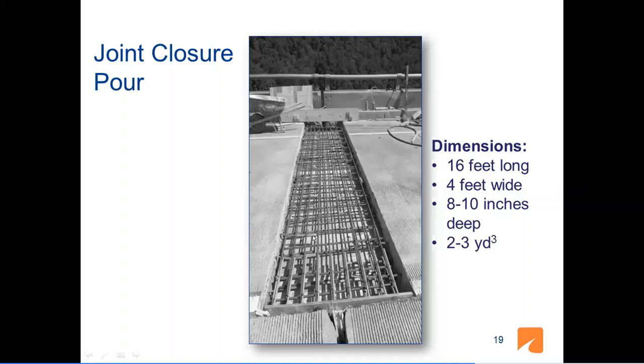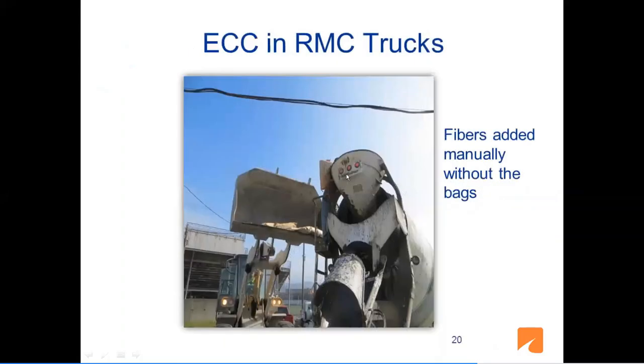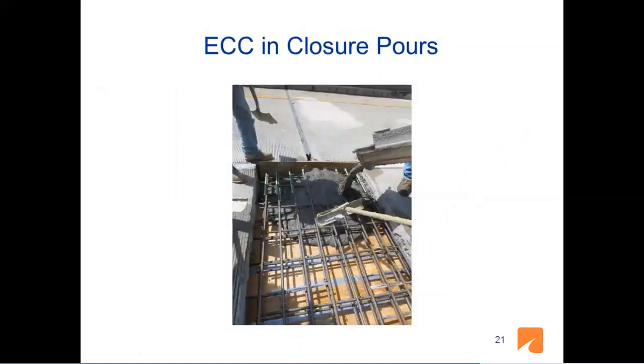And in these examples, as you remember, in the shear keys, we were talking about cubic feet, little amounts, less than cubic yard. But in these closure pours, we were using cubic yards of material. We were doing two at a time. So we used ready-mix concrete trucks. And fibers, as you see somebody here, adding fibers. Here's a bag of fibers. As I told you, this bag has 40 pounds of fibers, and we use one bag per cubic yard.